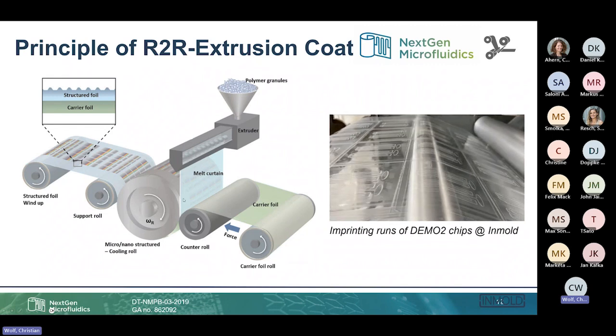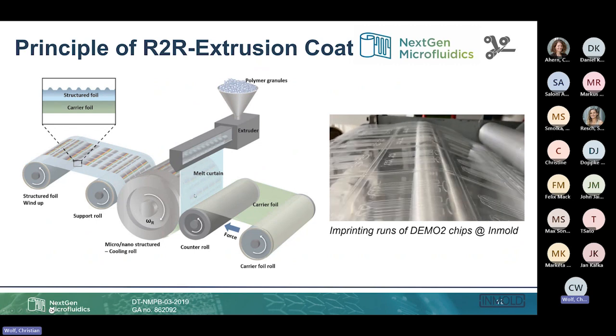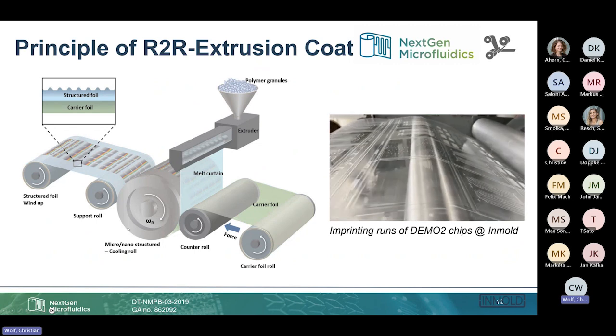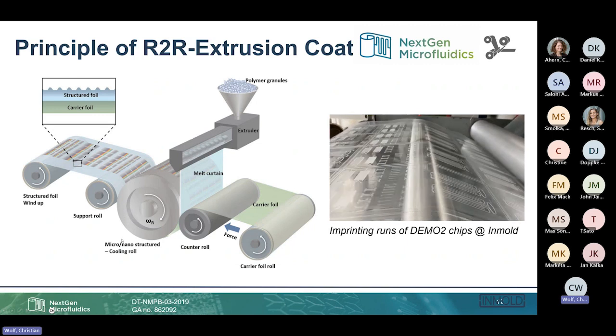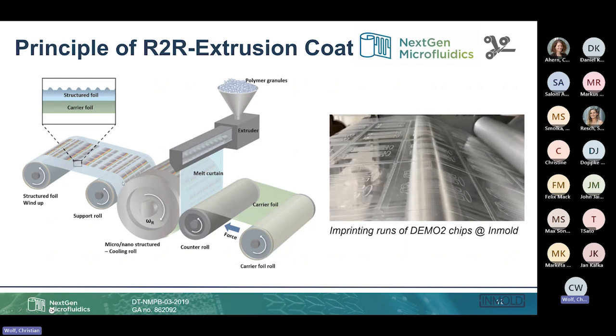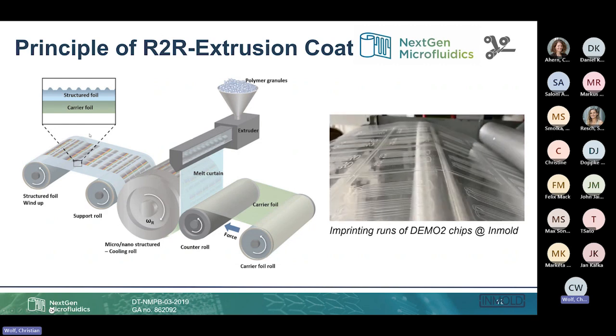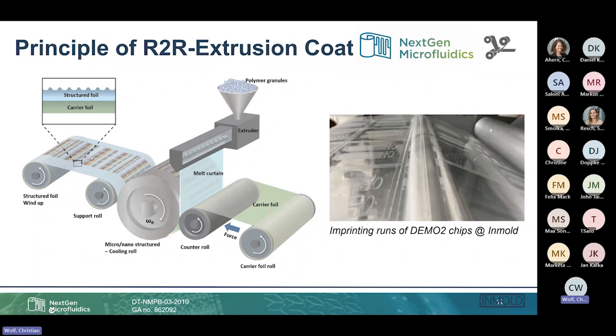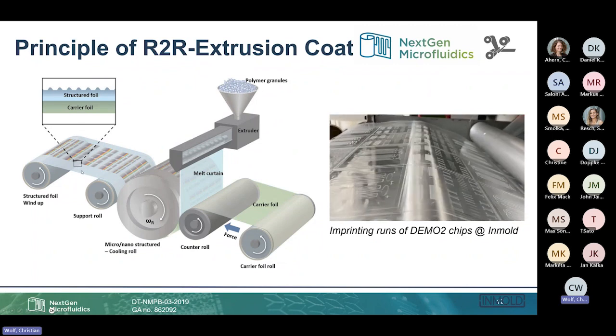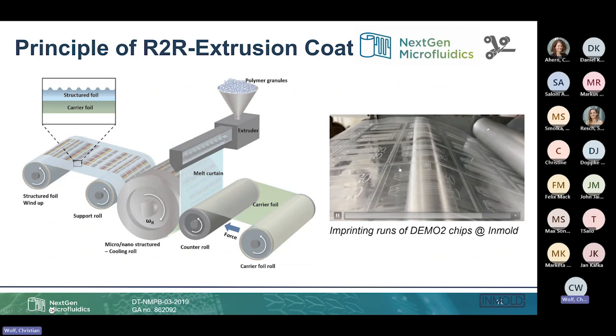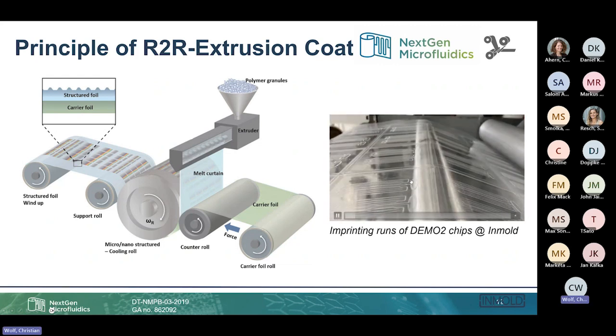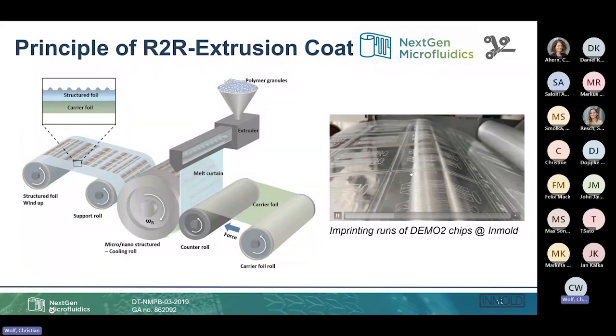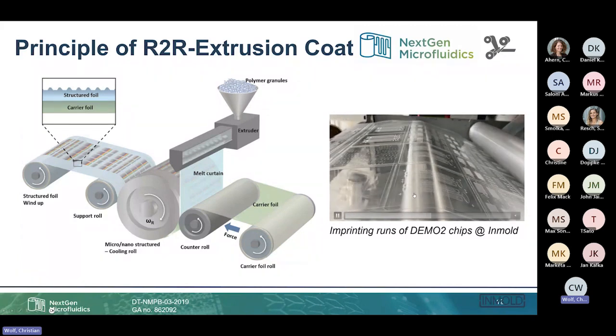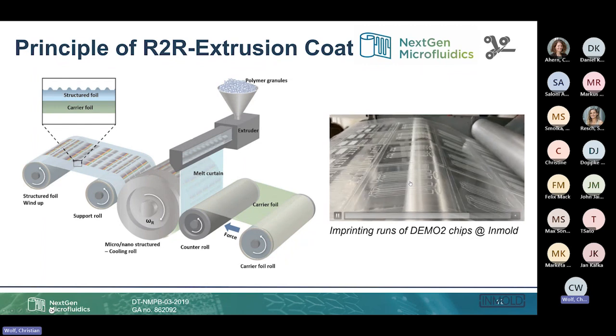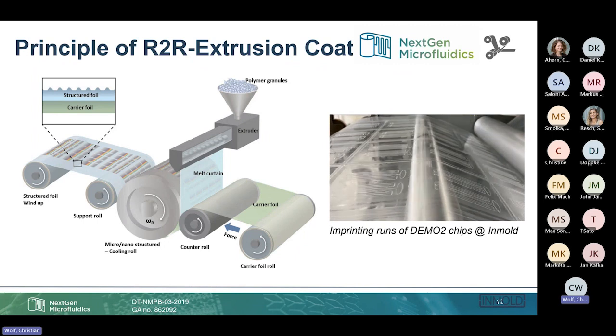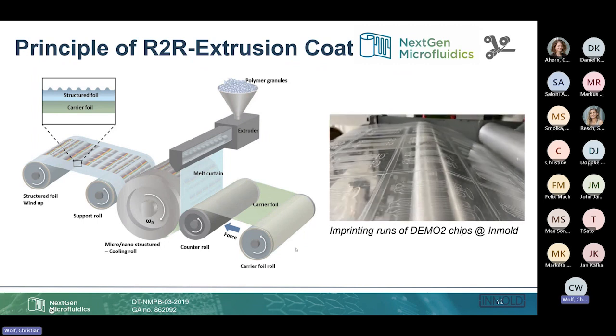And then you directly press your structures, while it's still warm and soft, into this polymeric material. And while the roll moves, the thermoplastic material cools down and hardens, and then you have your structures, the structured foil and the structured microchannels, realized on this carrier foil. So for example, here on this side, you can see a video of the demo chips, which were then produced with this extrusion coating material. So there you have some kind of thermoplastic polymer as a matrix material and not an acrylic resin, polystyrene or something like that.